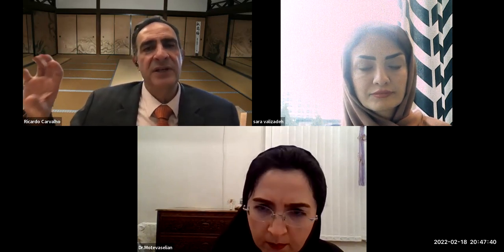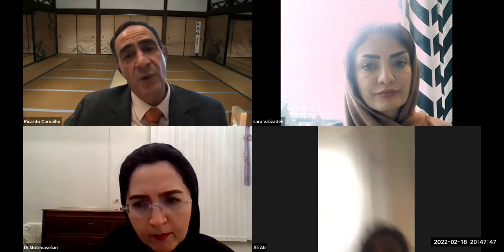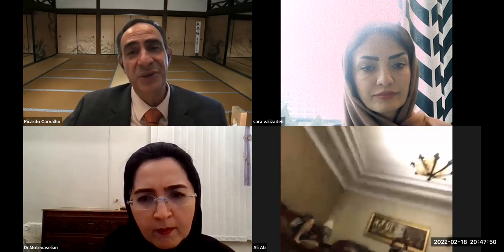So that reduces opacity right there. Also, they have modified the mole percent of yttria in these zirconias. Instead of 3%, they raise it up to 4 or 5% mole. The end result is that, remember that for YTZP, you have less than 15% of cubic phase. With these new materials, you have way more cubic phase, and that's why zirconia is more translucent.